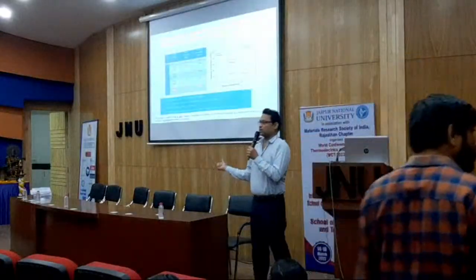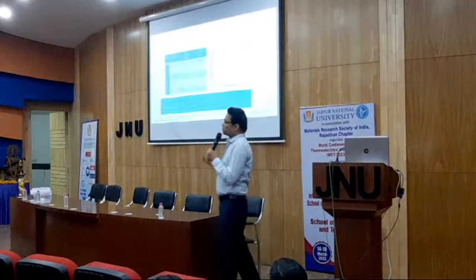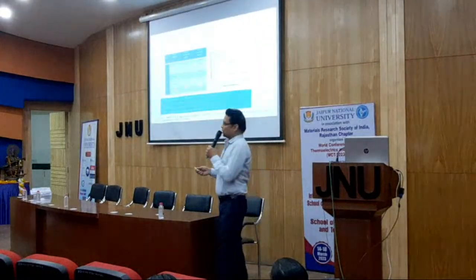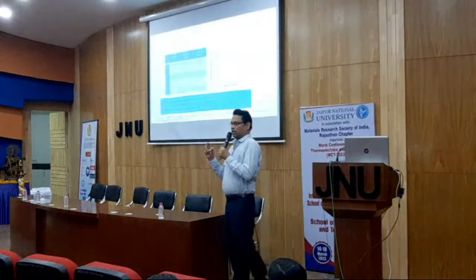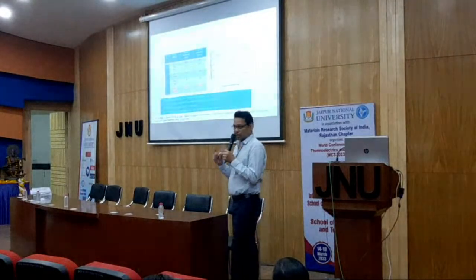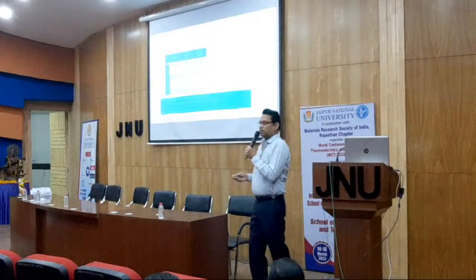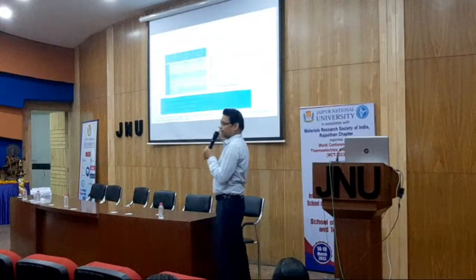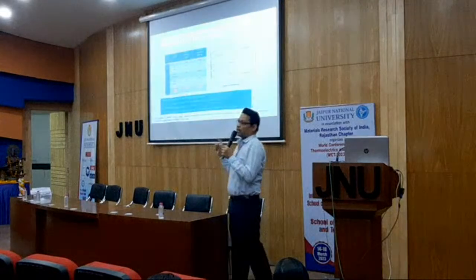which is by the novel approach of doping 10 mg of reduced graphene oxide with the bismuth telluride during the in situ synthesis, not like making two materials separately and then a nanocomposite. That will not work. We tried, right? So during the synthesis of this bismuth telluride, you take the reduced graphene oxide and dope 10 mg of it to get a unique morphology structure that will have a high ZT value because of higher electrical conductivity, the presence of graphene, and due to the phonon blocking phenomena, thermal conductivity reduced to 0.248, right? So whatever achievements we planned, it is successful. Our experimental results confirmed that we have high electrical conductivity and very low thermal conductivity by utilizing graphene as a dopant.